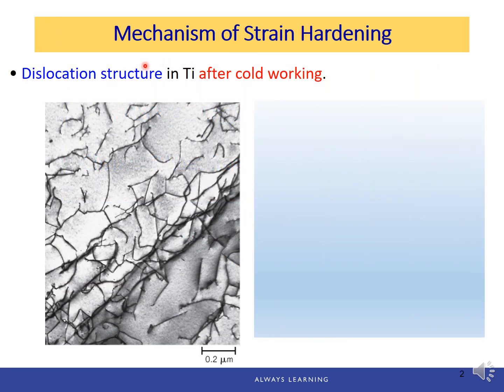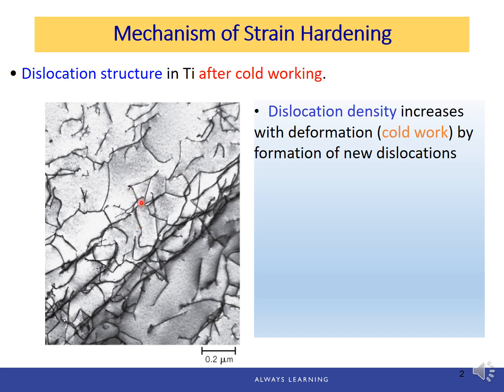In the last lecture, we learned the strengthening mechanisms. One of the strengthening mechanisms is strain hardening or cold working, which is used a lot in industry to form material into desired shape. And here is the dislocation structure in titanium after cold working under microscopic examination. So you can see those dislocations.